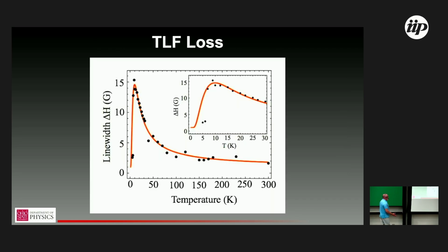Okay, and then the final question to ask as a function of temperature is what happens to the line width, and this was a plot that maybe both Greg and Dennis showed. And since Dennis is in the audience, I will let him answer any hard questions about the model. But the orange curve represents a fit to this idea of two-level fluctuators or paramagnetic spins that are providing increasing damping as temperature goes down as they polarize. And so more of them are available to execute a spin flip. So they're more efficient at scattering magnons. And in the model, the turnaround is as you start to freeze magnons out.